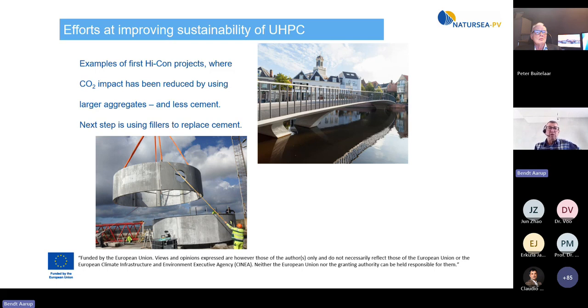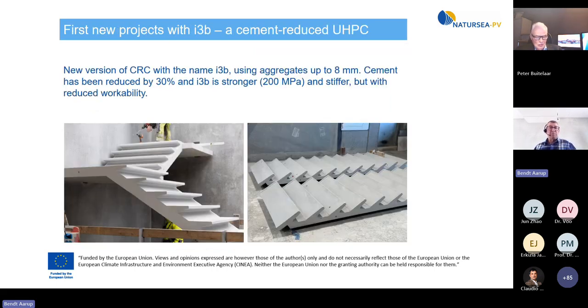Another way is to introduce fillers to replace cement, or we can use some of the new cements that are put on the market. Traditionally, we've used a CEM1 as basis for UHPC, but in February this year, we changed to a CEM2. So combining the large aggregates and the CEM2, we reduce cement content by about 30%. And cement is responsible for about 62% of the EPD carbon footprint. So it's really something that has a large significance.